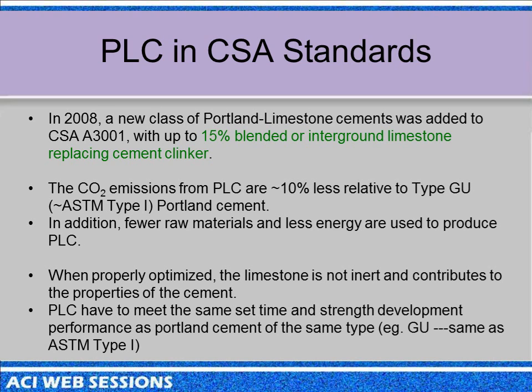Normally, Portland cements contain up to 5% interground limestone. In Canada, they've been doing that since the 80s. ASTM's had it since 2004, I believe. AASHTO M85's allowed it since 2007. So, in addition to reducing the CO2 emissions by grinding some limestone in with the clinker, you also make the limestone deposits that the cement plant's sitting on last longer, because you don't have that reduction in volume when you calcine the limestone. So they can actually increase the life of their quarry somewhat.